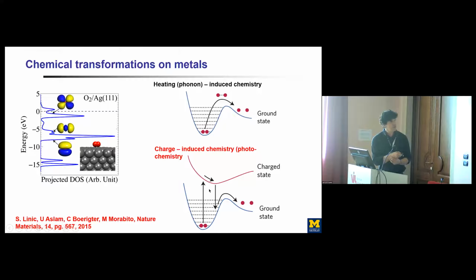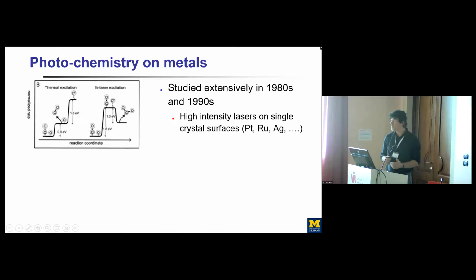Now, the difference here is that you actually can selectively put that energy in a particular chemical bond, and you can selectively activate that chemical bond without heating the entire nanoparticle. Well, there have been a number of really careful experiments performed, shedding light on this mechanism. I show work of Gerhard Ertl here and some of his co-workers, in which they show that if you run a thermal reaction where you have a ruthenium surface and you deposit carbon monoxide and oxygen on it, and you thermally heat that surface, you have a desorption of CO that takes place before oxygen desorbs, and you basically have no reaction. You don't get CO2. You get CO coming off and then oxygen coming off.